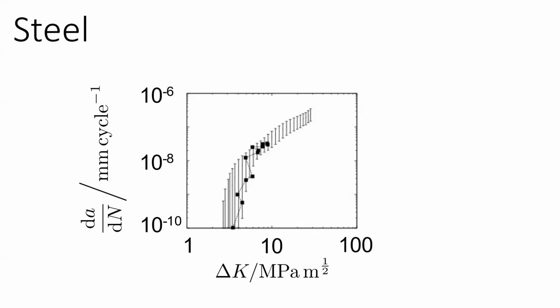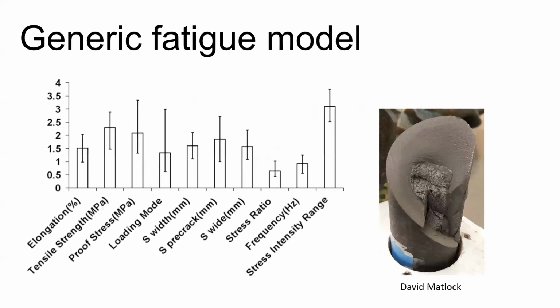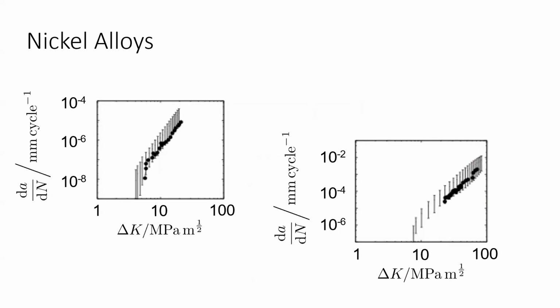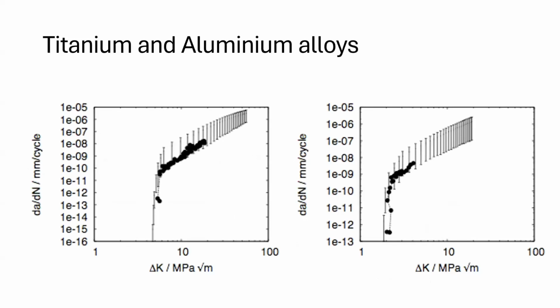But I'm going to show you something really crazy. This is entirely a model based on steels, no other metal. But I'm going to show you that it works extremely well for nickel, aluminum, and titanium. And the reason, I'll go back here, is that none of the inputs actually say that they are specifically about steels. These parameters apply to fatigue in anything. And therefore, we thought that the model should work for anything. And here you are, nickel alloys and titanium and aluminum alloys. Quite remarkable that you can estimate for things which were not in the database if you design your model carefully.